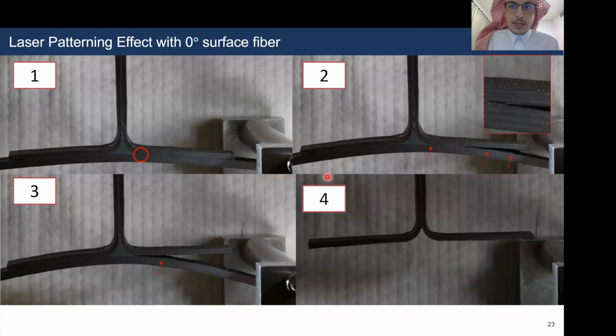And to look at why the 0 degrees patterning provided an enhancement in the toughness, we analyzed the images taken during failure, and we noticed what is known as an adhesive ligament. An adhesive ligament is when the crack propagates and stops for a certain reason, and then it initiates from a different region. So as we can see here, there's a first adhesive ligament that happened. Following, a second adhesive ligament happened here, and then the third here, and then the fourth was the final one that happened here or here. After the fourth adhesive ligament failed, it met the first adhesive ligament, and sudden failure happened for the T-joint.